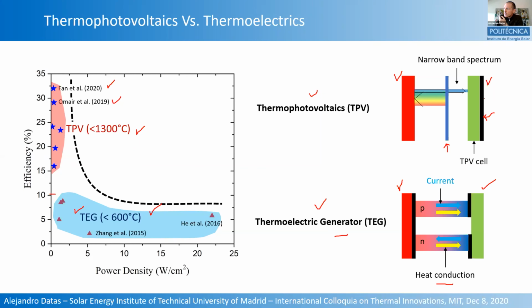And well, the tendency to increase the efficiency basically is to make this spectral control as efficient as possible, and this enables to use higher bandgap materials. But this again increases the efficiency. That's okay, but the power density is quite limited. Typically, it's lower than 1 watt per centimeter squared. So the question now is whether we could go to this region here. So the question will be if we can develop devices that can operate in this region, very importantly at low temperatures, where most of the thermal applications exist.